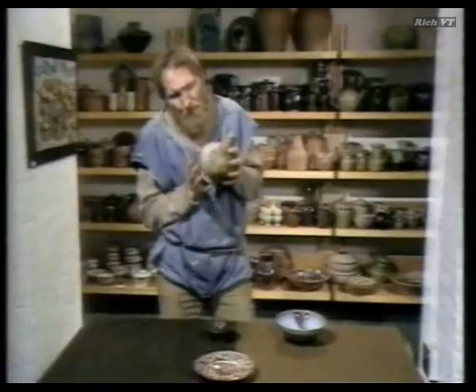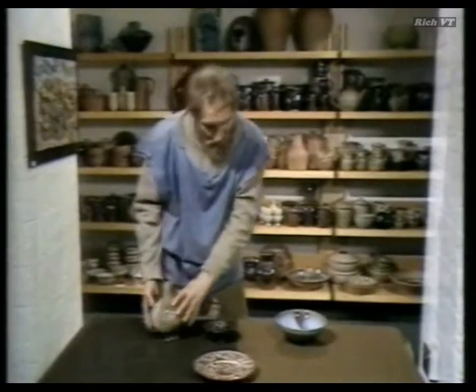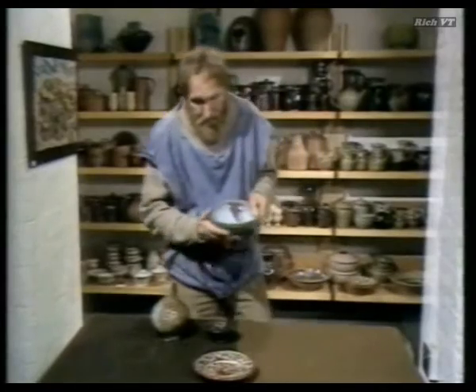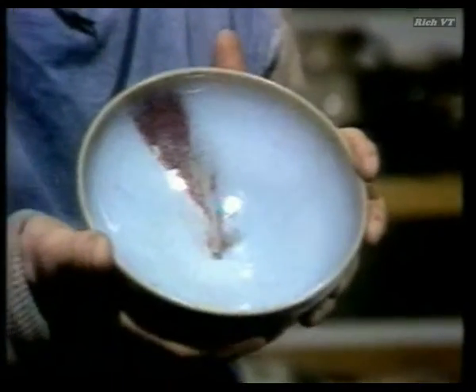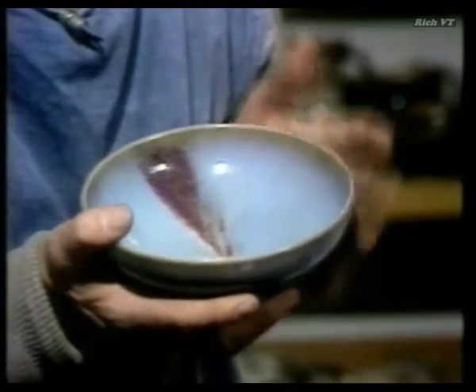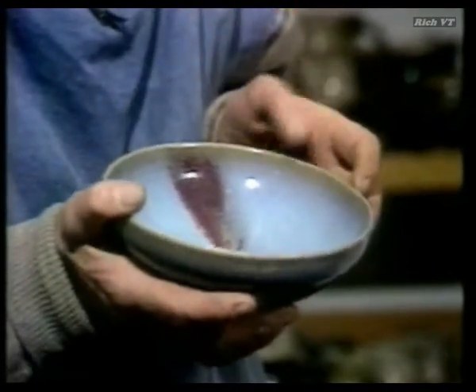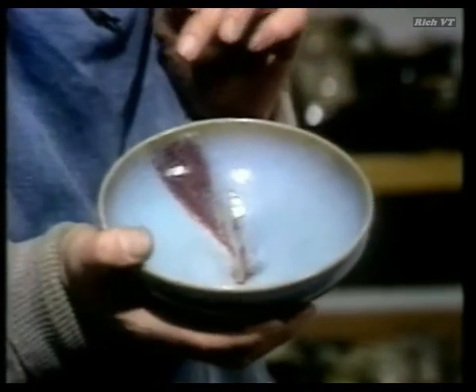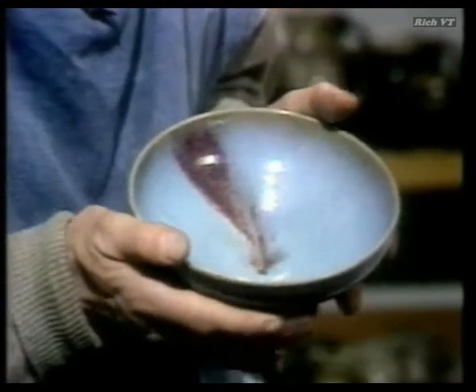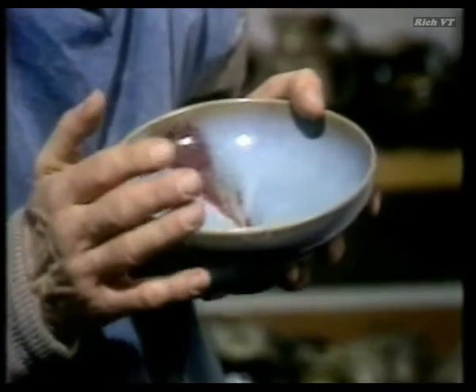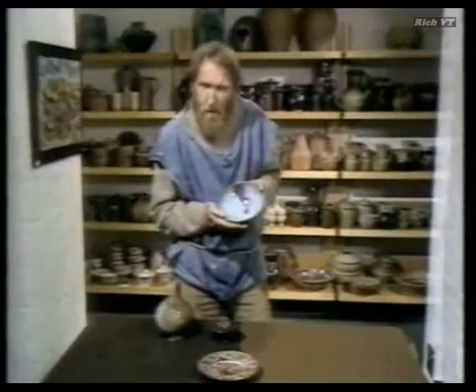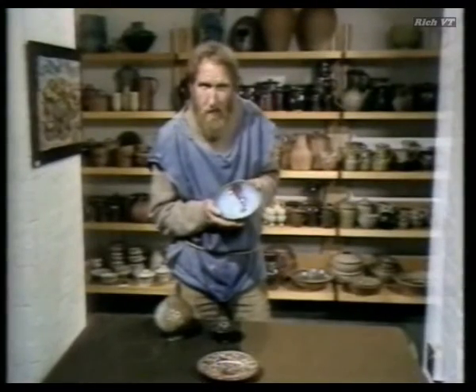It covers every surface. By contrast, this Chun bowl from Sung China of the 12th century AD, you may wonder, was that splash a mistake? I don't believe so. It's copper, reduced copper, that's why it's red. But the glaze is blue. Now, we've said that cobalt gives you blue, but there's no cobalt in that glaze. It's one of the really magical effects of glazing. It's an optical blue, blue light.